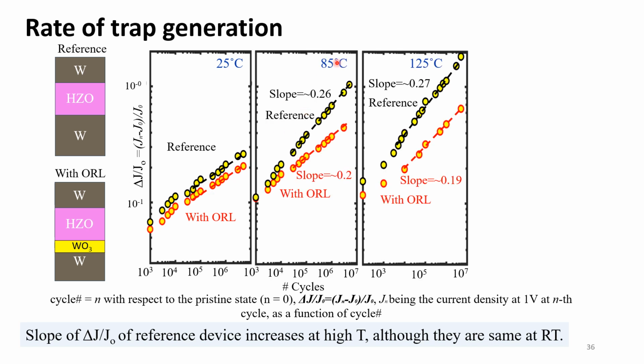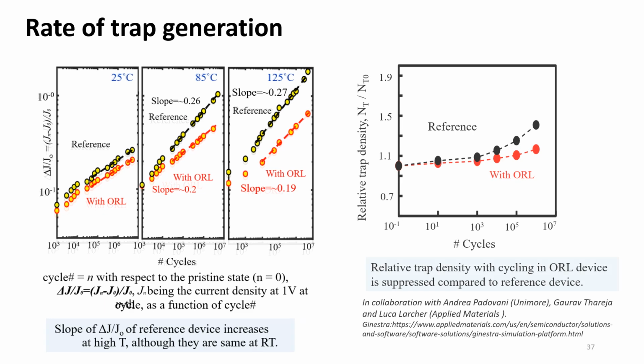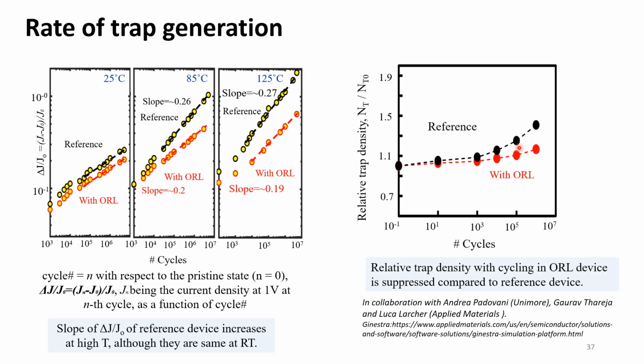But as soon as we go to higher temperature, say 85C, the slope of the reference device increases compared to the ORL device, which tells us that the trap generation rate increases in the reference device at higher temperature, and this is true for 125 degrees Celsius as well. We again used Ginestra to find the relative trap density for both the devices, and we could see that with cycling the relative trap density in the reference device increases, whereas in the ORL device it is getting suppressed with cycling. So here we could clearly understand that due to the presence of the tungsten oxide layer, the trap generation with cycling is getting suppressed, for which we are getting improved endurance in these devices.